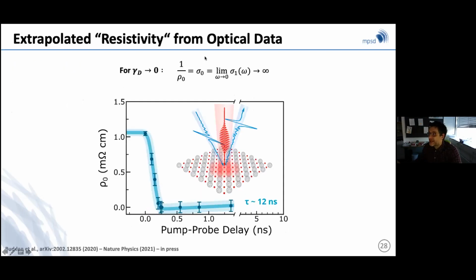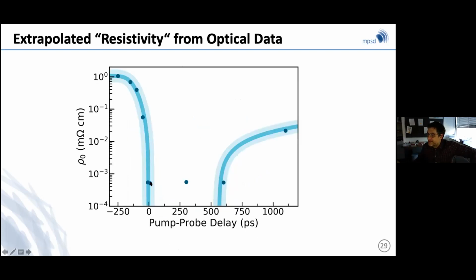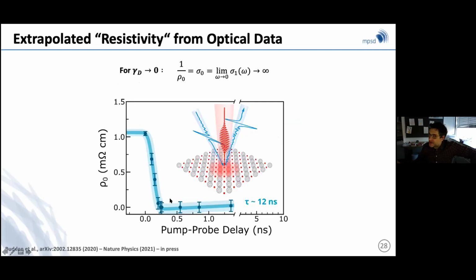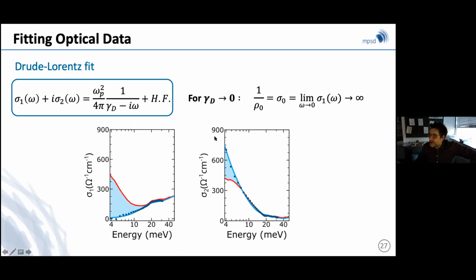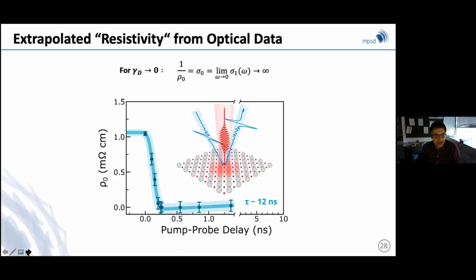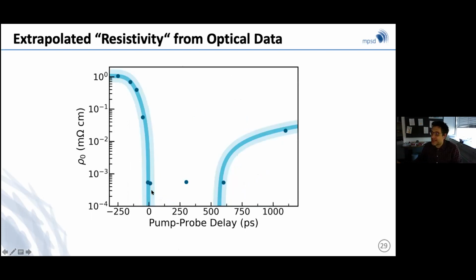And I can predict that the extracted sigma zero, the extracted rho zero, which is the inverse of sigma zero, goes from 1 milliohm per centimeter to something that is compatible with zero. And that lives for about 1 nanosecond. Again, I'm repeating things that I've shown you already. But what these optical data show is that if I could measure the DC resistance with leads, I should see a conductivity that drops at least 4 orders of magnitude. Now, the error bars here, so my ability to check zero resistance, is connected to the lowest frequency at which I'm measuring here. Of course, the conductivity cannot be assessed to be 0 if I'm only measuring down to 1 terahertz. Okay, but this is a pretty promising observation. I expect this thing to be in the micro-ohm per centimeter range.